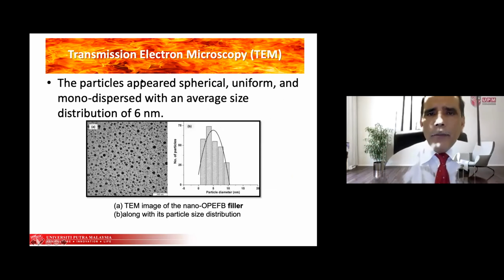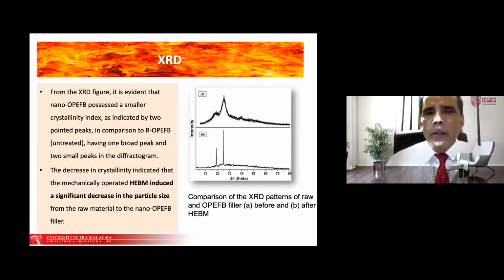And we checked the size through TEM images, and we found that the lowest size we get is 6 nanometers, but there is a range of sizes after the crushing. It may be 40 nanometers, 60 nanometers. There are different sizes out there. So because of that, we plotted the number of particles in that TEM image. And we also did the XRD of the nanofillers, and we found that the decrease in crystallinity indicated that the mechanically operated ball milling induced a significant decrease in the particle size from the raw material to the nano oil palm fillers.